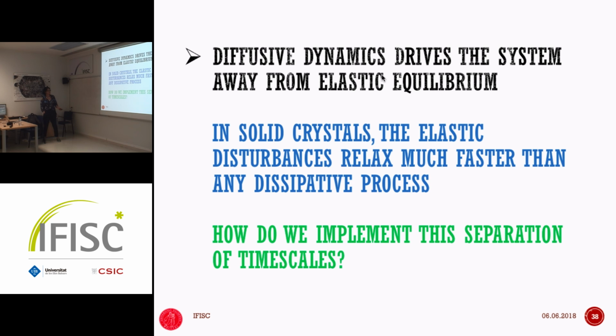So let me tell you a little bit about the last part, where we want to now introduce a new variable in the system that is going to constrain the mechanical equilibrium on the whole time. Because what I've shown you is that with this dissipative dynamics, we are producing stress, we are producing dislocations, but they're all slaved to the diffusive dynamics. In reality, when we deal with real crystalline materials, the elastic stress relaxes much faster than any dissipative motion because you have the vibrations, and the elastic vibrations die out much faster than any diffusive process. So you would assume that there is a huge separation of timescale between the diffusive relaxation of the density field and the elastic perturbations. And how do we implement that?